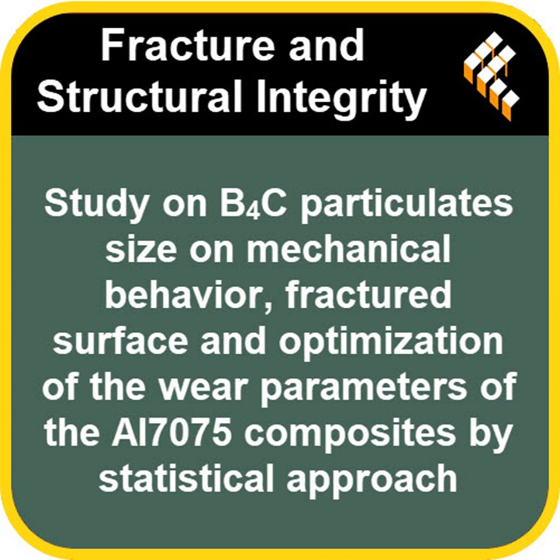Essentially, yeah, but it's very controlled. You preheat a crucible, melt the aluminum alloy, add the B4C particles, carefully measured, of course. Then you heat it further, stir it at a specific speed for a specific time to make sure everything's mixed evenly, nice and homogeneous, and to break up any clumps of particles. That's really important for a strong final material.